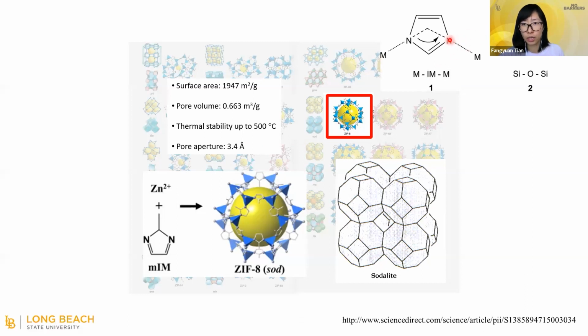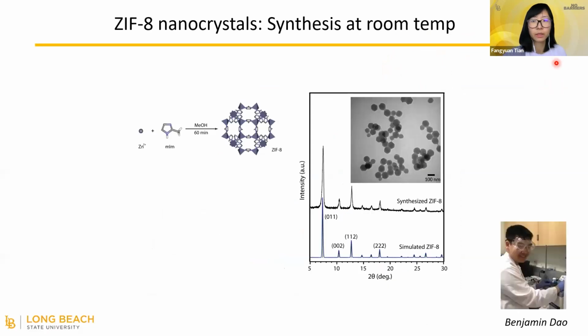So this is just a closer look at ZIF-8. It's called the zeolitic imidazolate framework just because the metal-imidazole-metal angle is similar to that of zeolite. In our lab, we synthesized ZIF-8 nanocrystals using a rapid method at room temperature. After synthesizing these in methanol, you'll notice that all of these particles are around 100 nanometers.